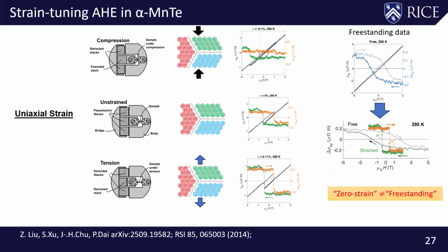And what this is suggesting to us immediately is that when you put a uniaxial strain, you actually detwin the sample, making a single domain sample, and therefore all the domain boundaries typically there in a 3-twin sample that would not contribute to an anomalous Hall suddenly disappear, and therefore your anomalous Hall effect becomes much sharper. Your coercive field becomes much less.